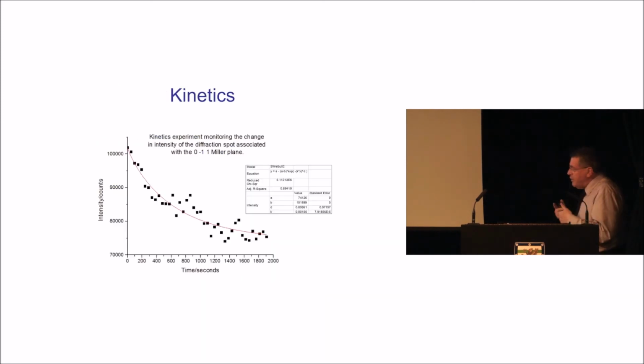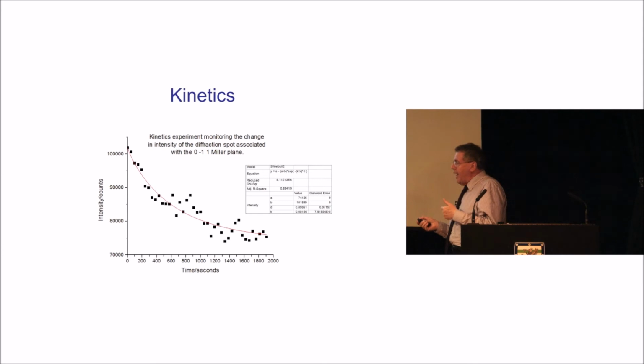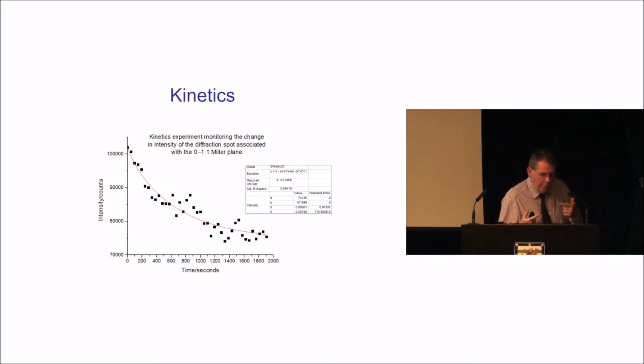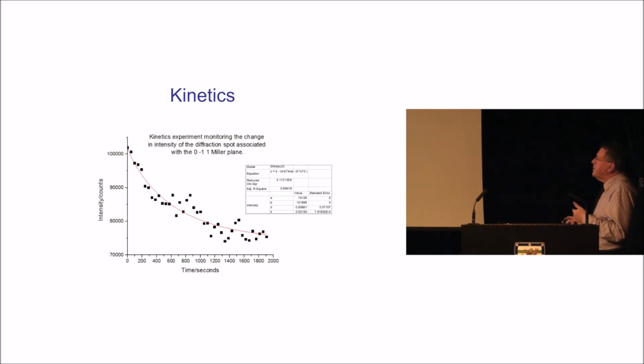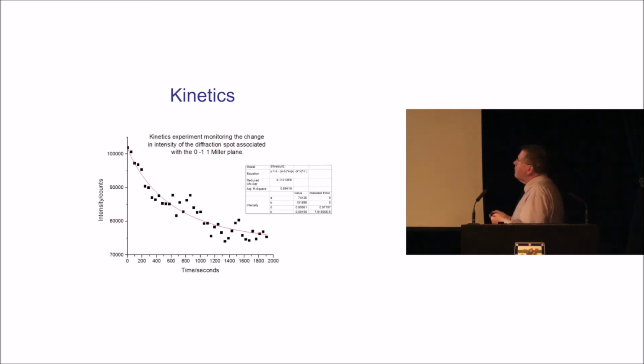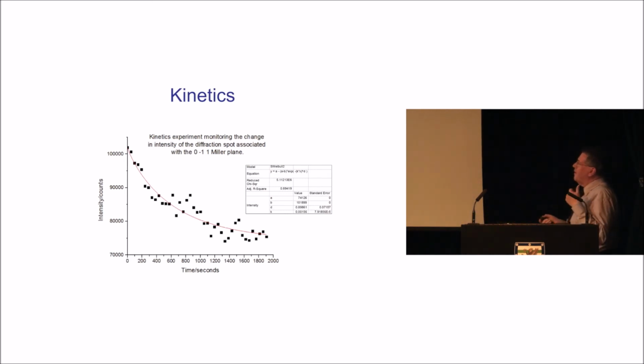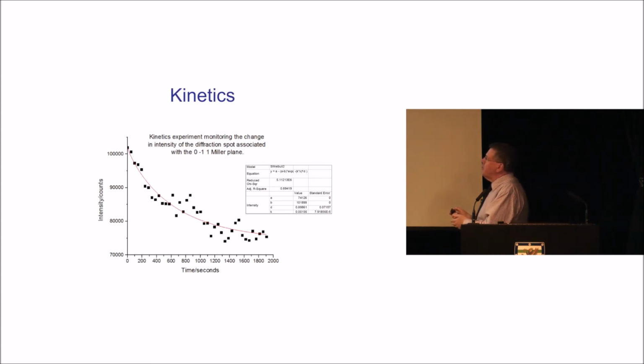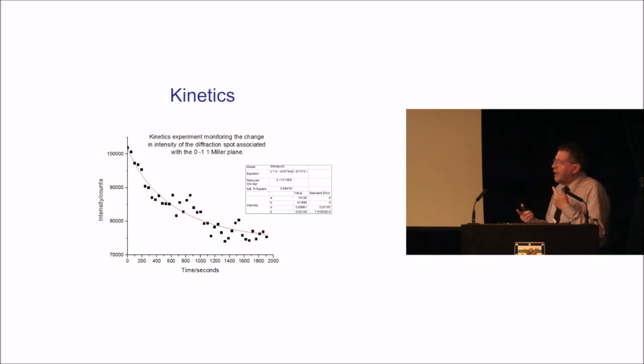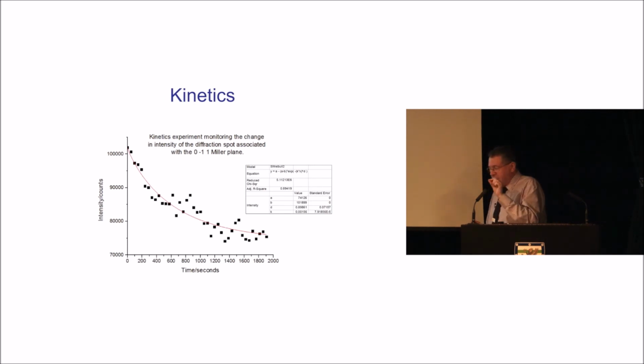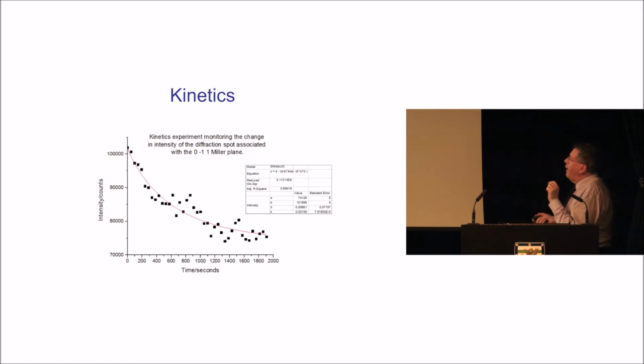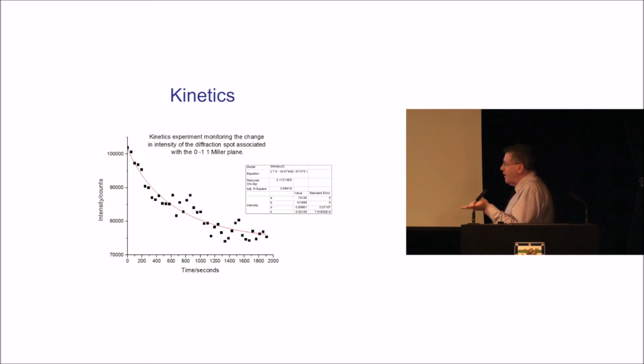What this allows you to do then is single crystal kinetics on these systems, so you can actually monitor a number of reflections to look at the kinetics. And what this tells us, I won't go through all the numbers on here, as I know Pete's standing up and looking nervous already, that effectively this number is the one we want to concentrate on. It's near 1 if you use the JMAK approximation for solid state kinetics. That's basically telling you that each photon interacts with one molecule. There's no cooperativity in these materials, and therefore you get an idea of what sort of experimental conditions you want for this process to occur.